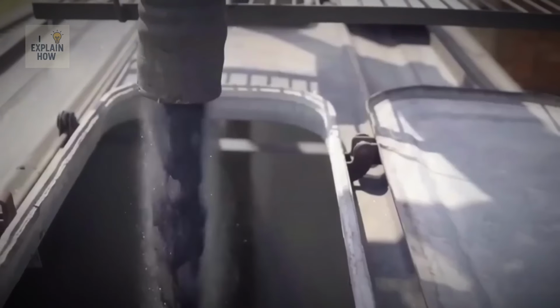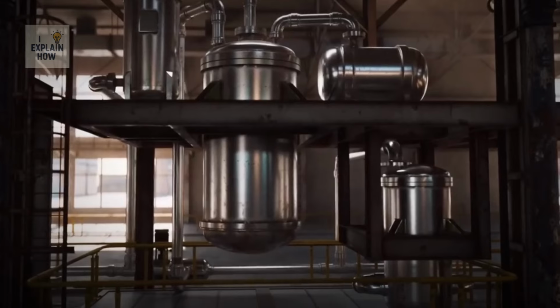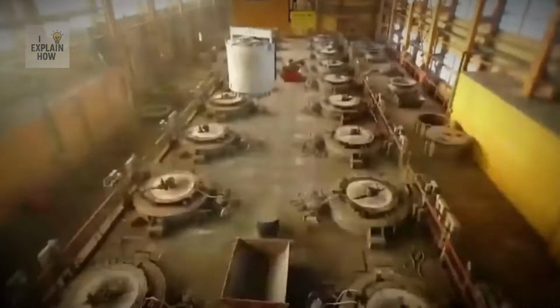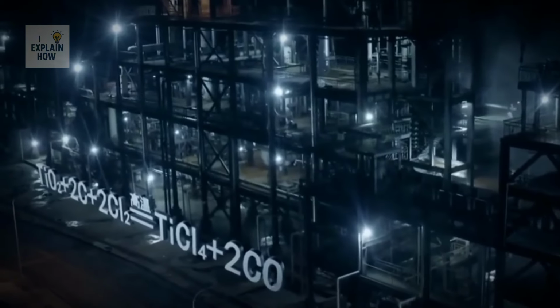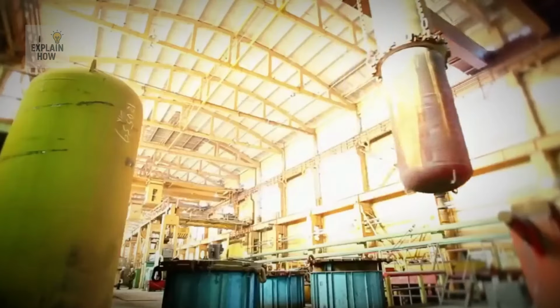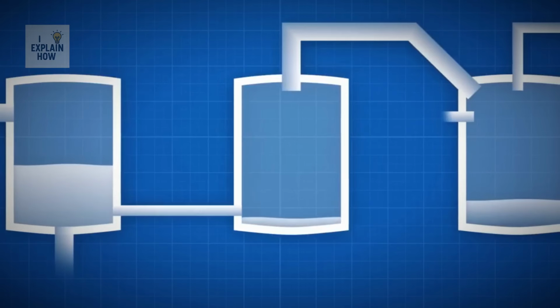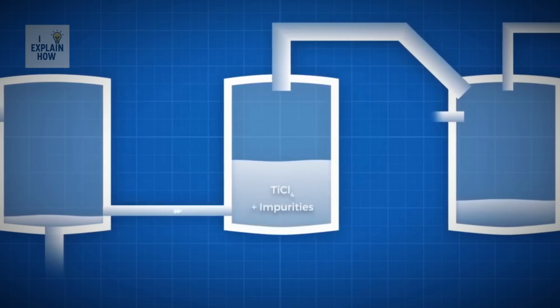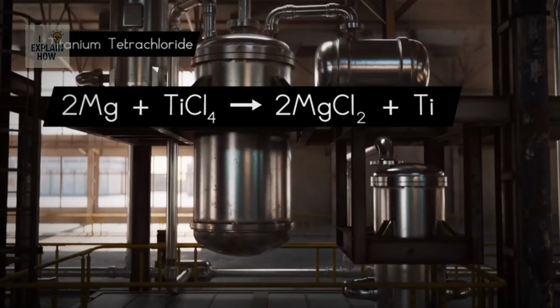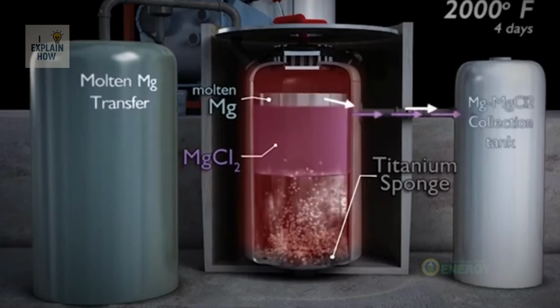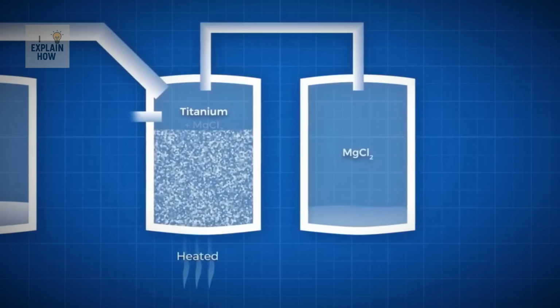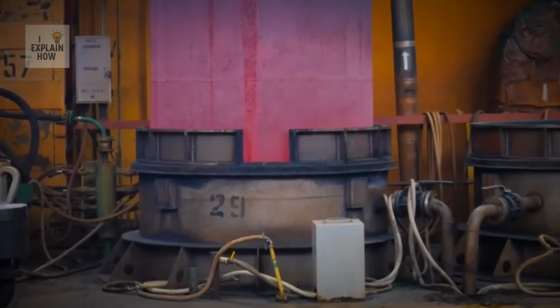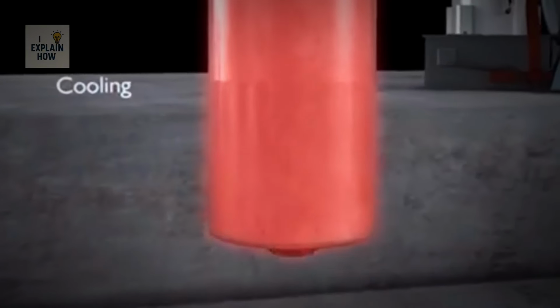We now have a powder of exceptional purity, but it is still only a promise of metal. To give it substance and strength, a ritual of fire and chemistry is required. A process so ingenious that it revolutionized metallurgy, the Kroll process. This process does not take place in open furnaces, but in immense, sealed steel reactors, veritable industrial vaults. Inside, the atmosphere is saturated with argon gas because hot titanium is so reactive that even air could contaminate it. First, titanium dioxide is heated to nearly 1,000 degrees Celsius, then exposed to chlorine gas. This reaction transforms it into a liquid, titanium tetrachloride.